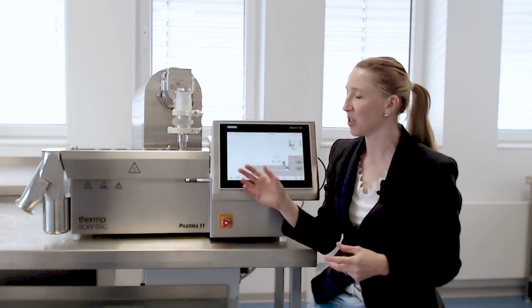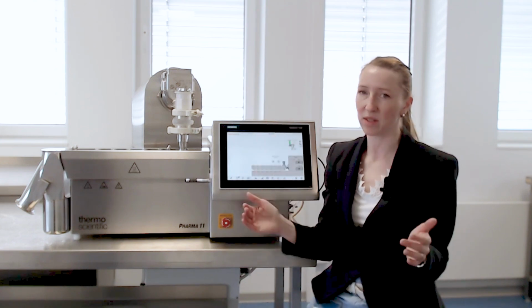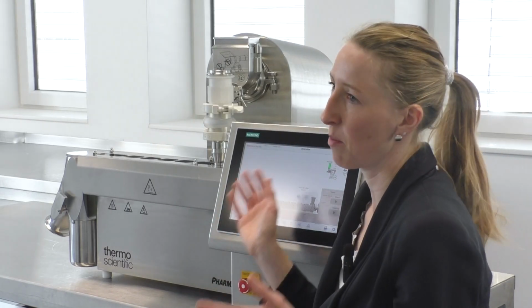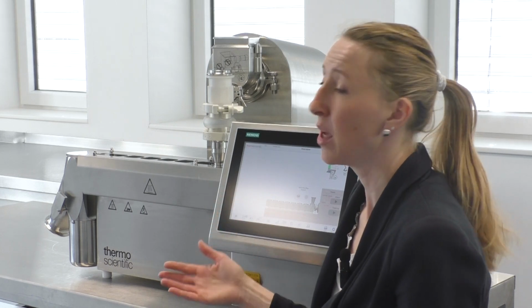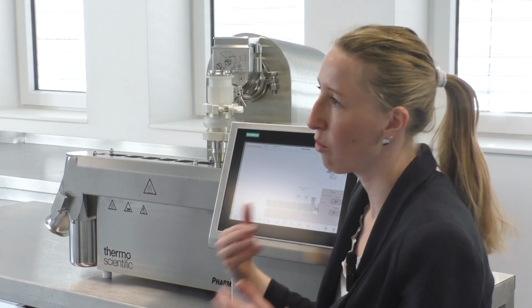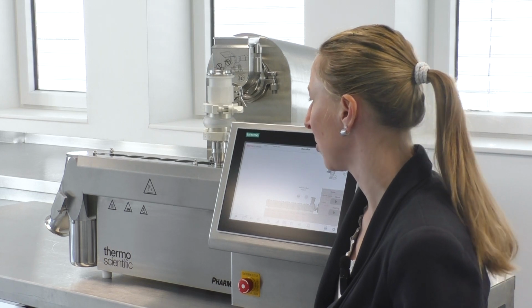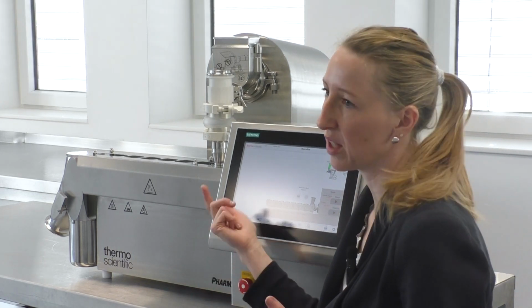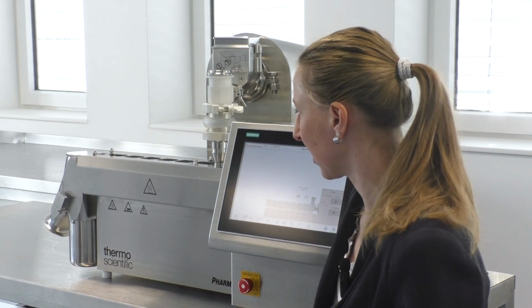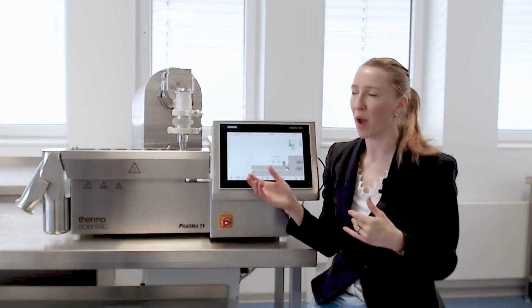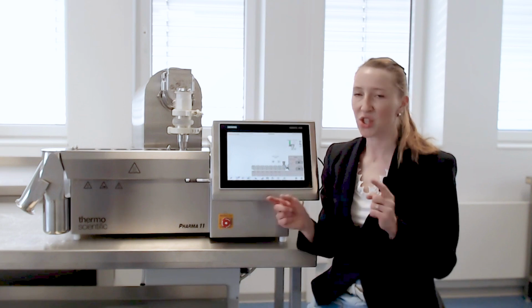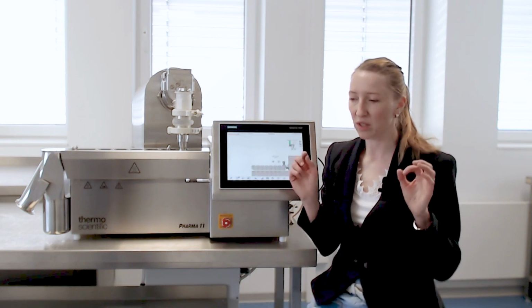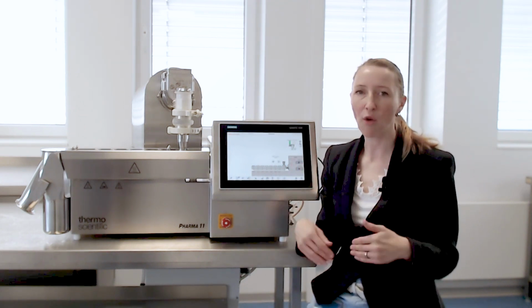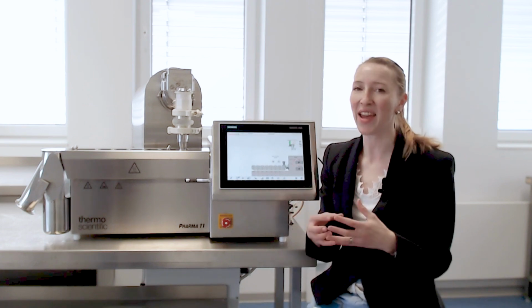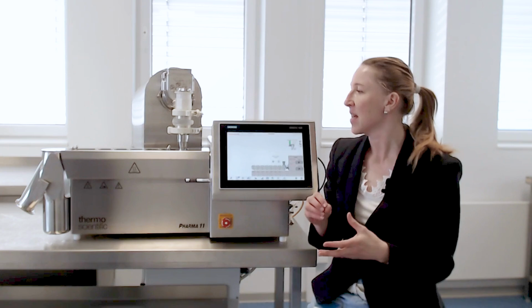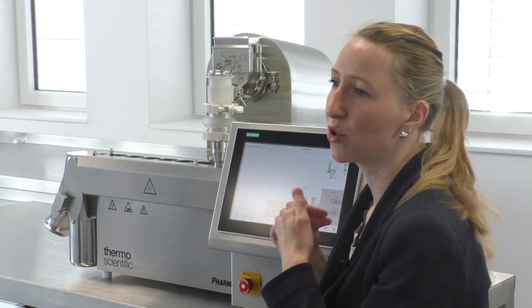It's not that we have one batch and this size is fixed, but we can decide how much material we want to process anytime. We just need to set the feed rate, so how much we feed into the extruder. And with this, we adjust the screw speed of the screws that process this material. And the nice thing is you can change, and this is what I also did in this research, I changed the settings continuously because what is very crucial for this process is how full the screws are, how much mechanical energy I introduce into that process. And this I could do on the fly.